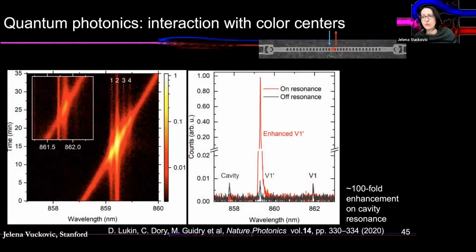And of course, the ability to do nonlinear optics on the same platform means that even if you work with optically interfaced spin qubits and quantum emitters, you can do all quantum frequency conversion on the chip, or you can also do nonlinear optic parametric down conversion based sources. And for interfacing with quantum emitters, we've shown that we don't really sacrifice the properties of quantum emitters once we make silicon carbide photonics. These are just very simple light matter interaction experiments where we tune a quantum emitter, the silicon vacancy in silicon carbide, onto a resonance, and we show significant Purcell enhancement.